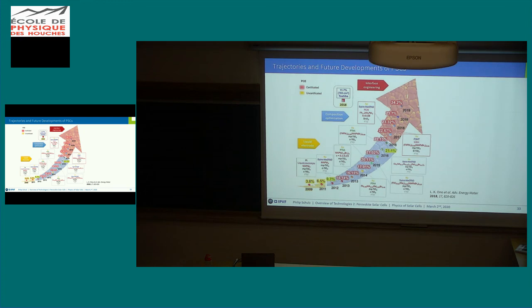You can see this is in somewhat chronological order, the difference between MAPbI3 that was started here, and then this cesium, methylammonium, formamidinium lead iodide bromide mixture. While I was at NREL, we actually called this the kitchen sink perovskite, because you pour everything together, stir it up well, and then make a film, and it works as a perfect solar cell with 20-something%.